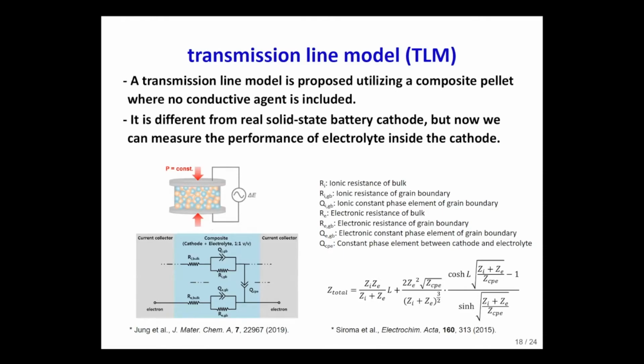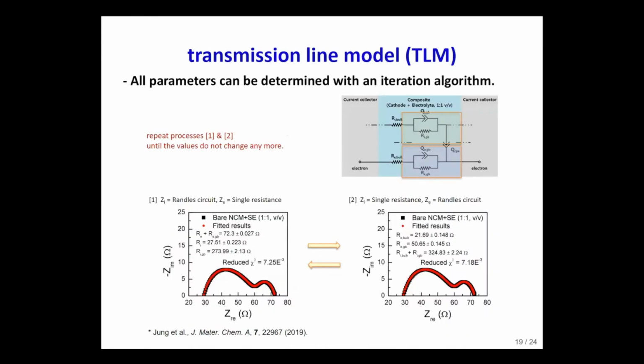If the electronic conductivity of the cathode is too good, this model does not work. So for the measurement, the conductive agent should be removed, and at least 50% of the volume should be occupied by the electrolyte. The actual curve fitting is very complicated, but it is achievable with an iteration process, for example. But there are many other methods for the curve fitting.